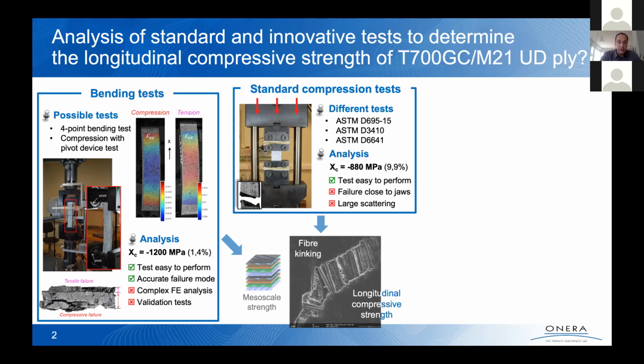Therefore, this test is pretty easy to perform. It's just a compression test with the pivot. And a good point is that you are able to measure the strain on the 2 faces during the test pretty easily if you use, for instance, digital image correlation. You can also observe, as it has been mentioned previously, where the failure occurs, which in that case occurs far from the jaws. So that's a pretty good point.